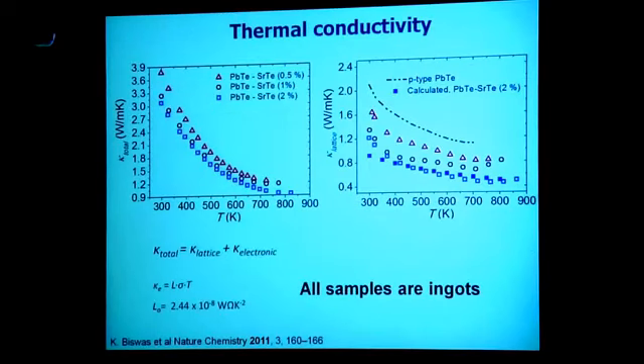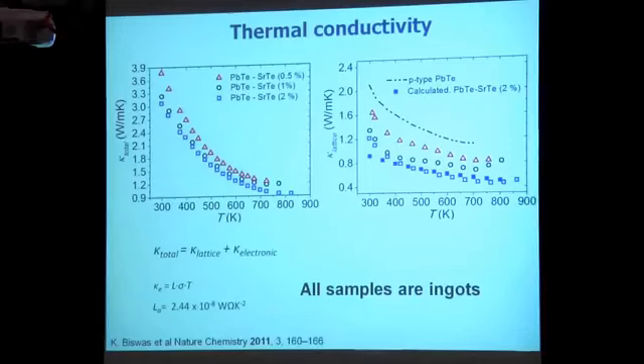The thermal conductivity is lower than lead telluride, but it drops as you add more strontium telluride. The lowest value, this is total, is for the 2%, and it falls below 1 watt per meter Kelvin. If you extract the electronic part, then you get these numbers, which is about 0.4 to 0.5 watt per meter Kelvin, one of the lowest lattice thermal conductivities for lead telluride. So you take the lead telluride value, which is the dotted line, and you bring it all the way down here. At the same time, the power factors are more or less the same, as if the lead telluride didn't know the strontium telluride was there. So this is a great combination.